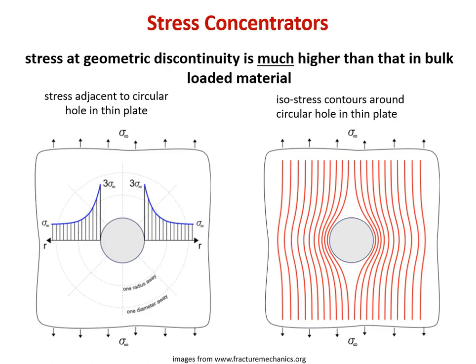So again, if we're applying 100 megapascals to the entire plate, you're going to have 300 megapascals right adjacent to that circular crack. Excuse me, circular hole. If it were a crack, it would probably be higher. And we will get to that in a minute.